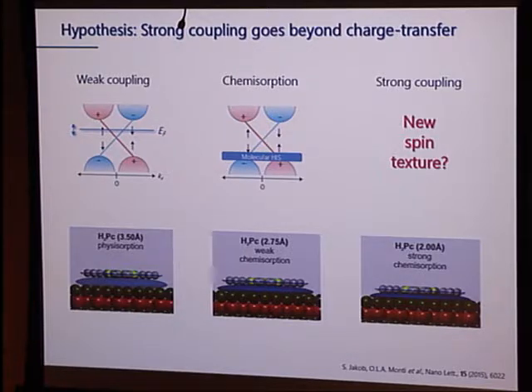Then let's take that molecule and get it closer to the surface. This is what's drawn here, and if I get it close enough, I'm starting to have some sort of bonding-type interaction. We would call that chemisorption, perhaps weak chemisorption. And usually the way that shows up is that you start mixing these localized molecular states with states from the surface. And the net result is exactly what we saw in the Alq3 cobalt case, where we had these hybrid interface states that appear. Those are usually not dispersive, so they show a flat band someplace inside the band structure.